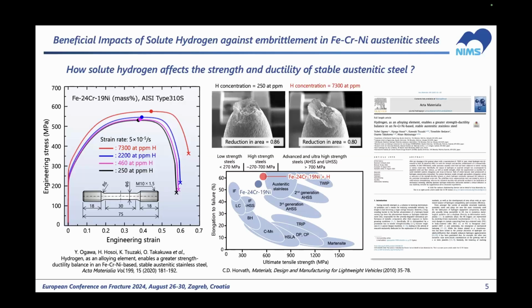What we did was just expose our tensile specimens to a gaseous hydrogen environment at elevated temperatures to attain a uniform hydrogen distribution in the specimen's gauge part. And after that, we did tensile tests. What happened? All the yield strength, tensile strength, uniform elongation, and fracture elongation were improved by the presence of hydrogen. So this was quite surprising for us at that time. And if we plot these properties on the well-known banana curve, the hydrogen moved the properties from the lower left to the upper right.